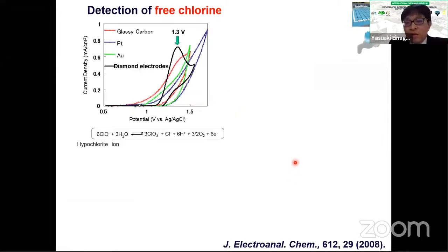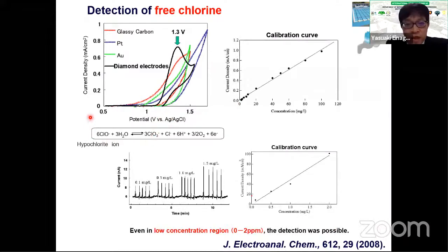Okay, so not only histamine, this is another example, chlorine detection. Chlorine is also very nice, because when we use conventional electrodes such as glassy carbon, platinum, or gold, as you can see, the oxygen evolution is observed around here. On the other hand, when a boron-doped diamond electrode is used, a very clear peak is observed, with no oxygen evolution. So this is very nice. And this is the reaction of the HClO oxidation.